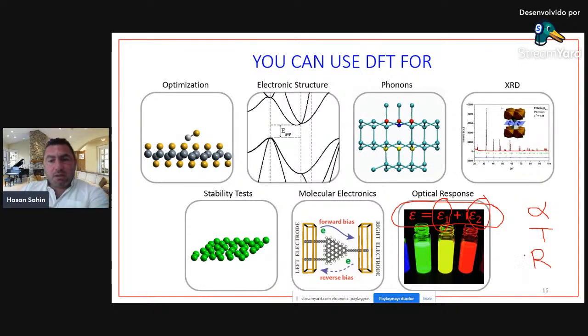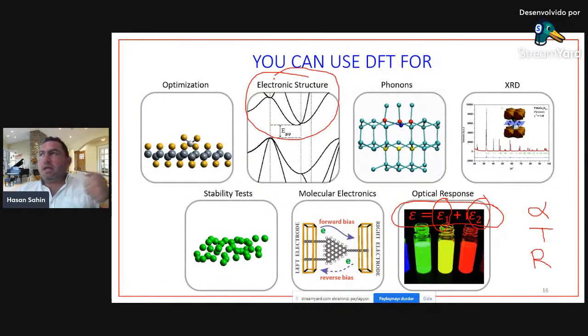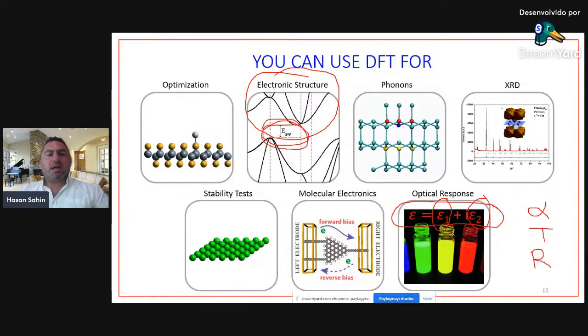And here, as you see, I'm always thinking about experiments. For the electronic structure, a photoluminescence spectrometer will measure this gap. Actually, this is an indirect gap which cannot be measured by PL measurement, only direct band gaps can be measured. But the electronic band gap will be measured by a spectrometer.